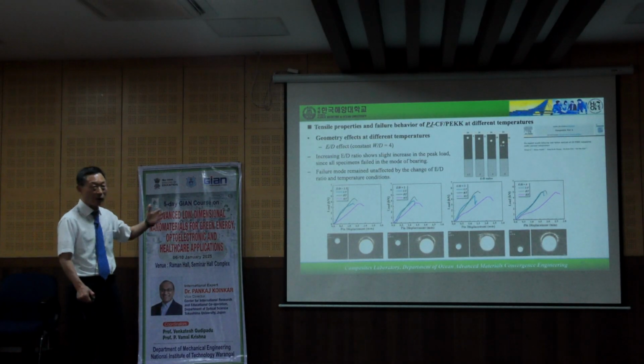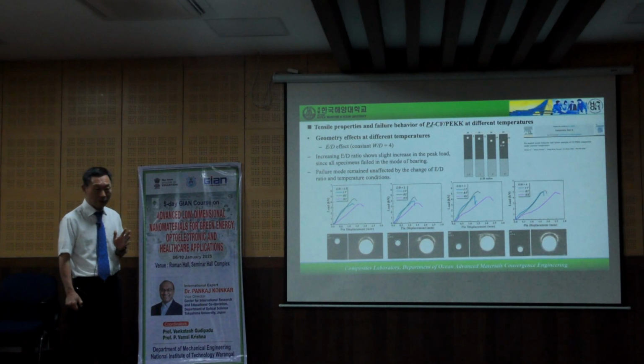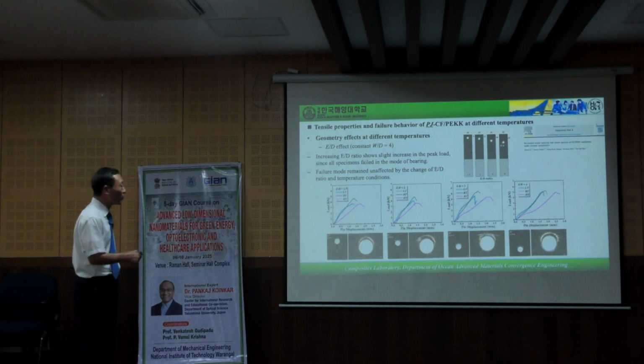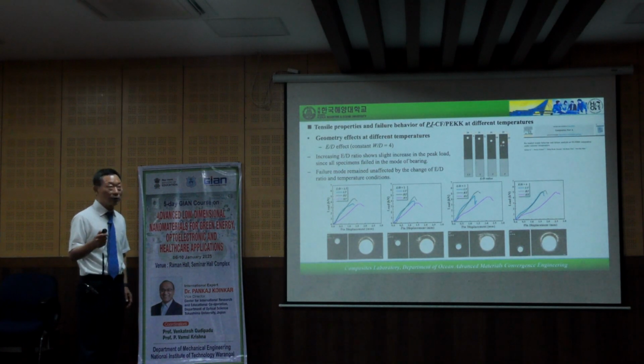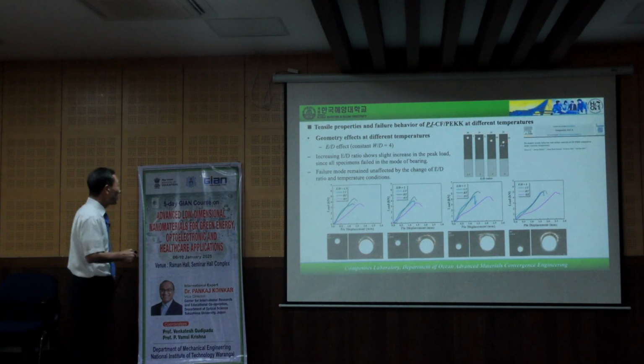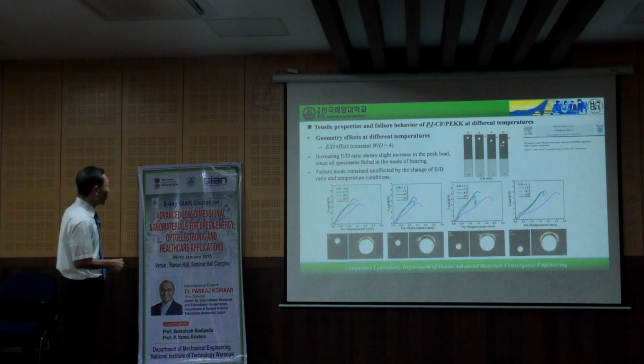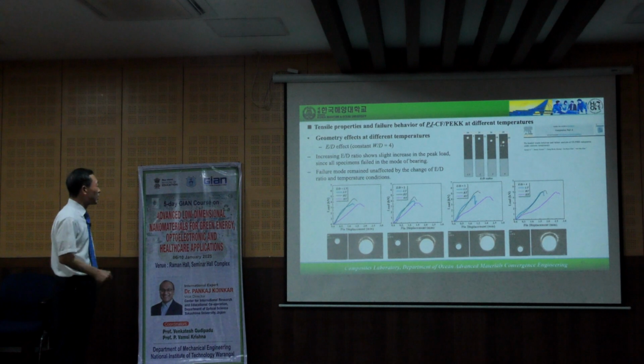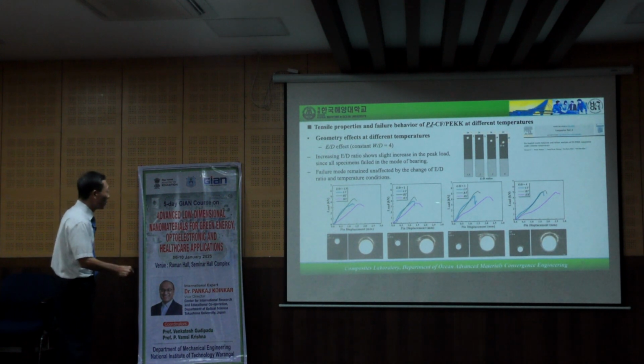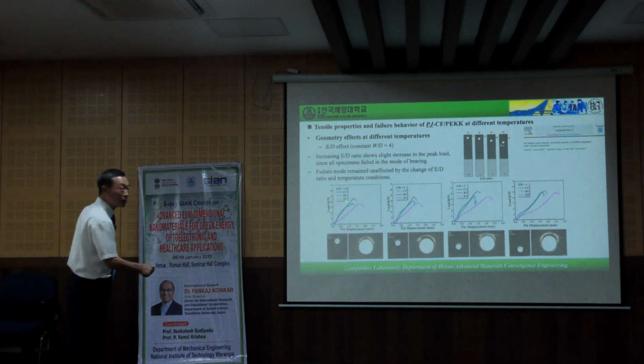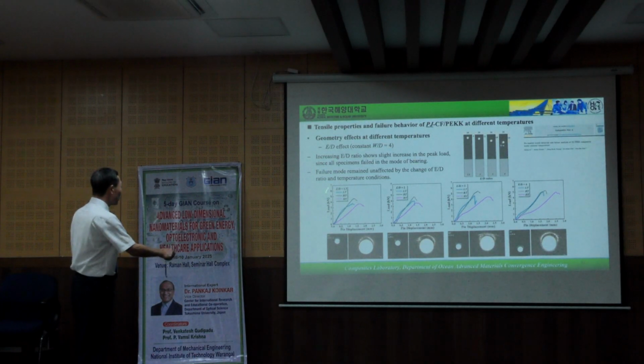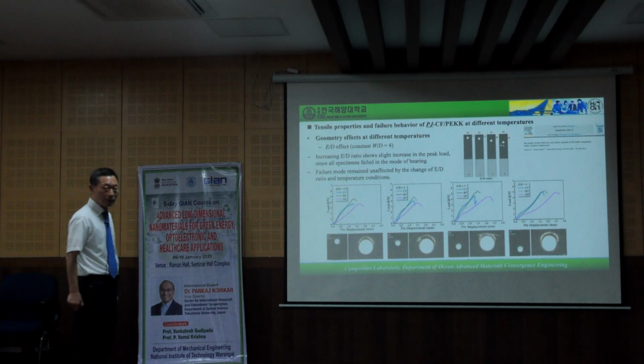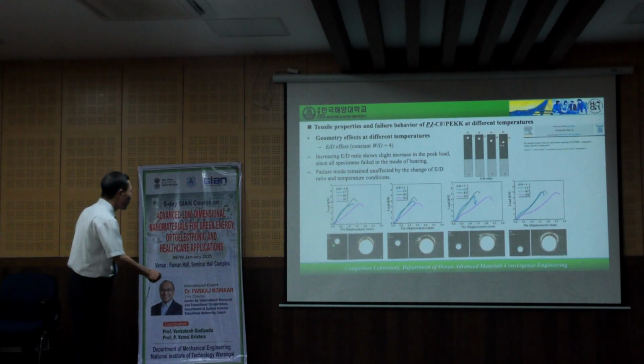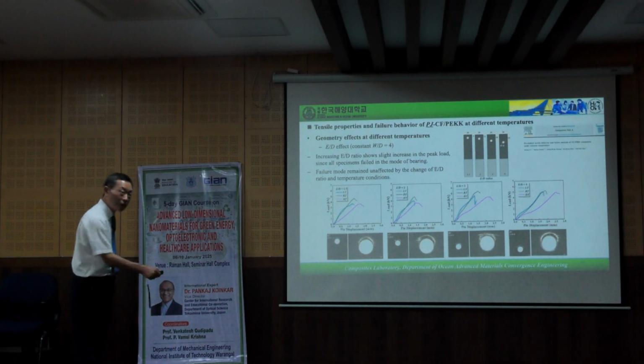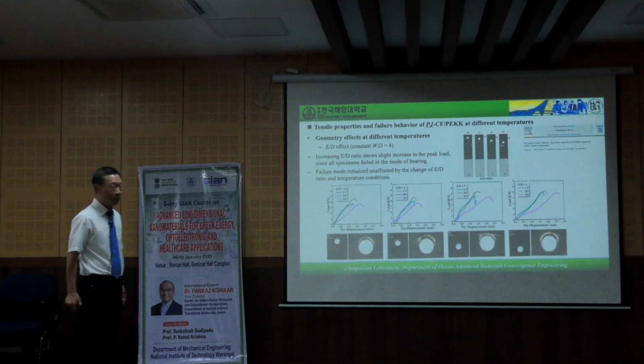Just before, we compared the W/D ratio. This is E/D ratio under W/D ratio, the constant ratio. Okay. So increasing E/D ratio shows a slight increase in the peak load. Just compare the peak load under the different temperature range. You can compare also the failure morphology pattern. Very similar.